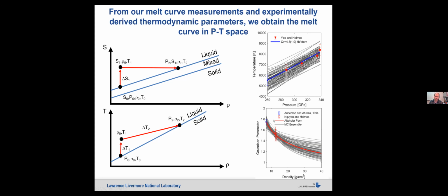And then also the Grüneisen parameter is really important over this pressure regime. In liquid iron, the most accurate data on the Grüneisen parameter at ambient densities was from Anderson and Ahrens in 1994, and then also the Nguyen and Holmes sound speed data along the Hugoniot in the same pressure regime. So then I fit an Altshuler form to this Grüneisen parameter as a function of density. And again, this is an extrapolation with a Monte Carlo error propagation across this data set. But the density range we're talking about in these experiments is 12.5 grams per cc along the Hugoniot, around 14 grams per cc at 500 GPa, and around 18 grams per cc at the highest pressures. So we're really interested in this regime of gamma, which is reasonably well constrained, even in extrapolation, by the data.